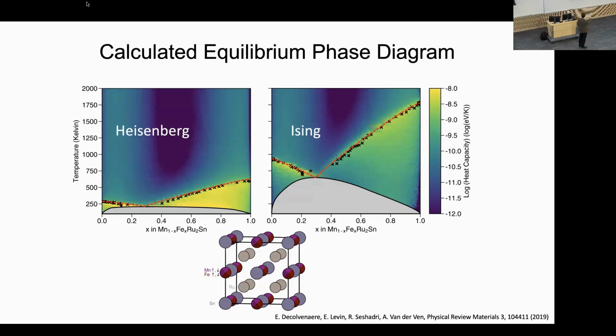And what you can see is, if you allow for Heisenberg statistics, the paramagnetic phase, which is a disordered arrangement of magnetic moments, is much more stable because when you have Heisenberg statistics, you have much more entropy because there's many more possible states of the magnetic moments. And so the Heisenberg statistics pushes these magnetic transitions to much lower temperatures. And when we actually do quantitative comparisons to experiment, we get excellent agreement if we compare these transition lines to actual experiments than if we do Ising statistics, which tells us that the physics of this material, the magnetic moments, are these continuous degrees of freedom. You have to really do the Heisenberg statistics to do the magnetism right. And it affects the rest of the topology of the phase diagram. It depresses this miscibility gap to much lower temperatures, which is a chemical miscibility gap.